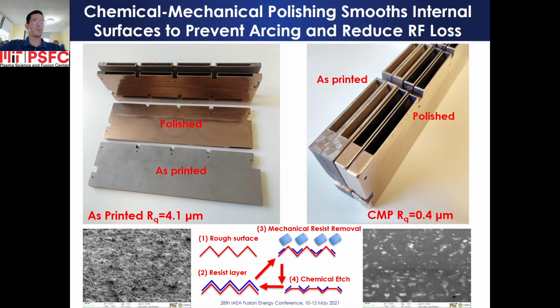Chemical mechanical polishing smooths internal surfaces otherwise inaccessible to mechanical polishing with a combination of chemical and mechanical action. A slurry of etching chemicals and abrasive beads are passed through the internal structure of the phase shifters and power splitters. The chemical etchant simultaneously etches and coats the copper surface with a chemical resist layer. The motion of the abrasive beads wears off the resist layer from the peaks, but not the valleys of the surface. Further etching of the peaks then occurs. This process is continued until the surface is polished flat.